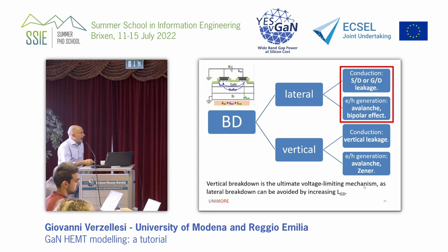Focusing on lateral breakdown, there are conduction mechanisms that can lead to breakdown, using an operational way of defining breakdown. The current reaches some level, the level that I decided not to be tolerable for my application. So we are using that definition for breakdown, that VDS can be limited by simply conduction, leakage current. And leakage can be source to drain leakage or gate to drain leakage.